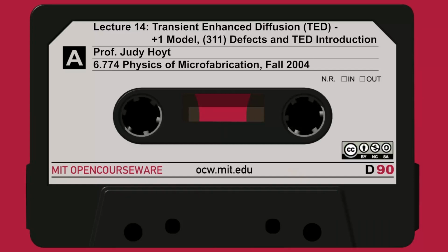It's a plot of the silicon self-interstitial density, in number of interstitials per square centimeter, contained in 311 defects. They're basically looking in the microscope and counting the density of 311 defects, and then estimating from their size and density how many interstitials are in them as a function of time at different temperatures. So here, let's take the red boxes.